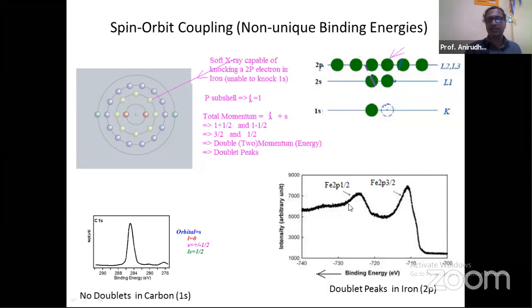So to contrast this with Fe, I have shown the carbon 1s peak, which is on the top left corner of this slide, which is from carbon. And then the X-ray was penetrant enough to knock out a 1s electron from this. So therefore, for this L is equal to 0. So you will get a single, unique value for your momentum and a unique value for your energy. And therefore, in your XPS peak, you will not see two different values for those binding energies. You will see only one unique value, which is what I have shown here. Whereas for iron, you will see a doublet.